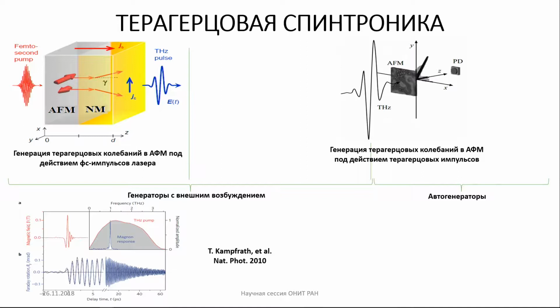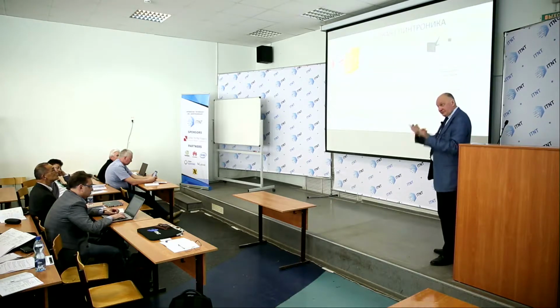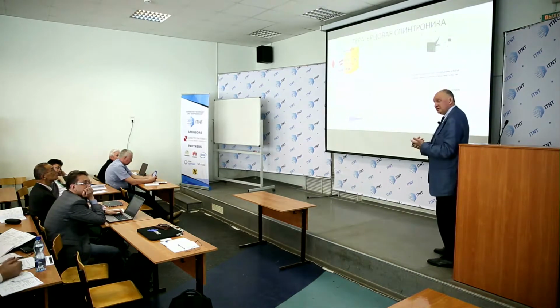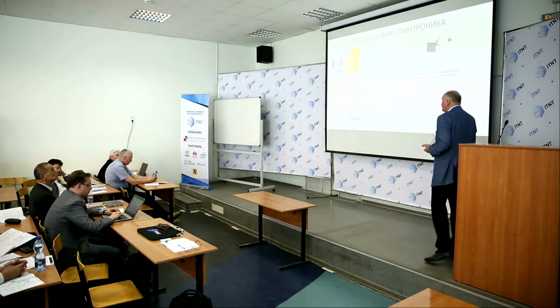If we put an electromagnetic field inside this material, for example, femtosecond optical pulses, then due to strong scattering it will excite spin currents of electrons, and these spin currents going into the antiferromagnetic material can change the value of magnetization. This change of magnetization in the antiferromagnetic material lies in the terahertz frequency range, so you can excite terahertz waves from this antiferromagnetic material.